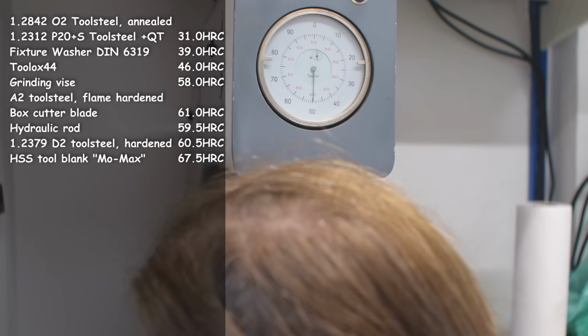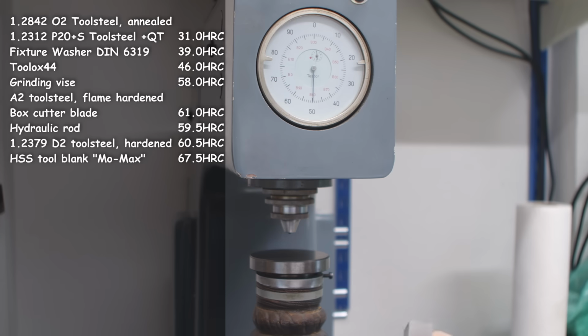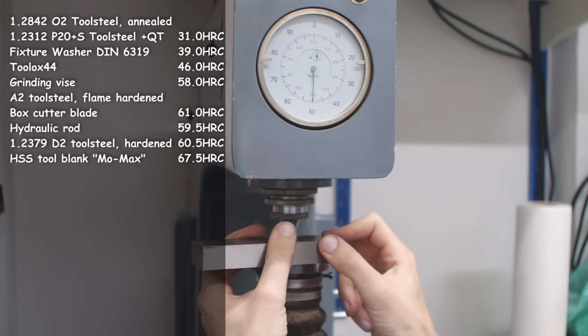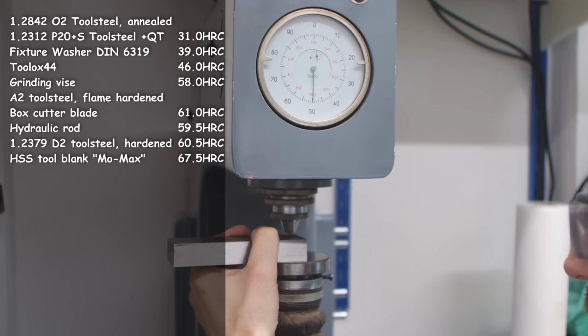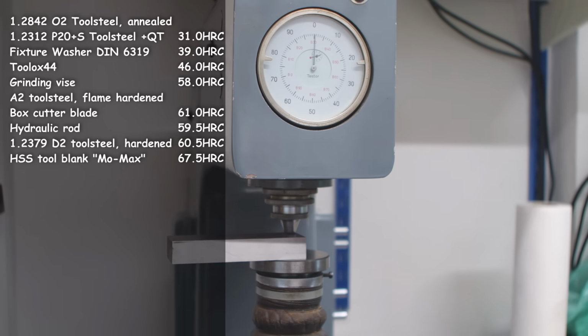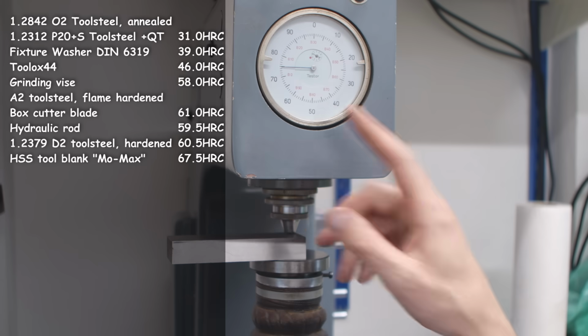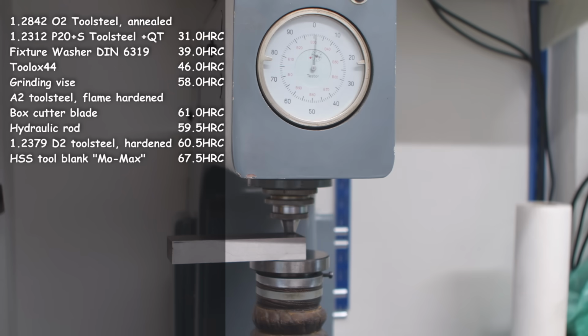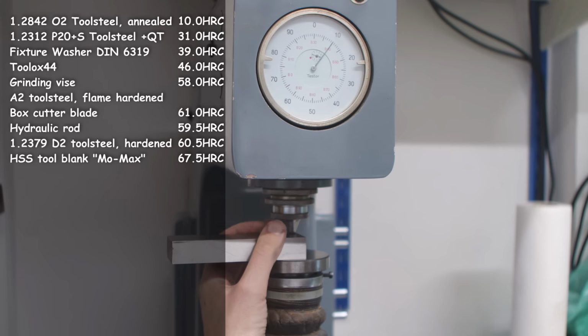And the last one is O2 tool steel annealed. This is how you would get it from your steel dealer. And as I said, tool steels without heat treat are kind of useless. Tool steel, soft, let's see. There is a lower limit to the Rockwell C scale where it doesn't make any sense anymore, and this is one of those cases. So let's see what we get. It's settled out. Yeah, 10 Rockwell C. It's kind of useless at this point.